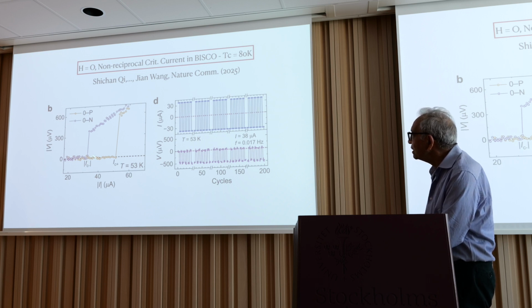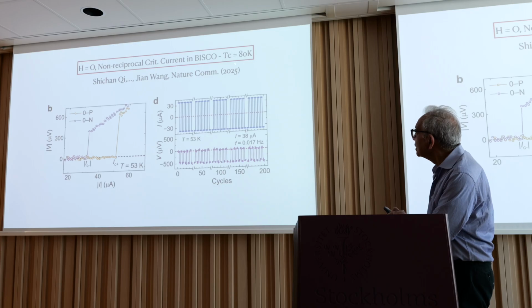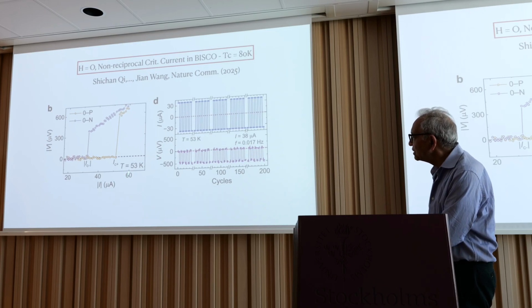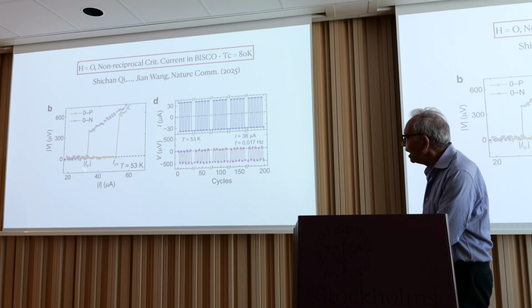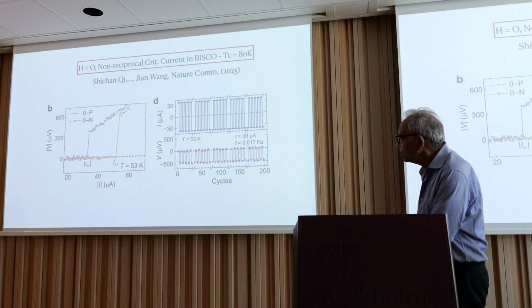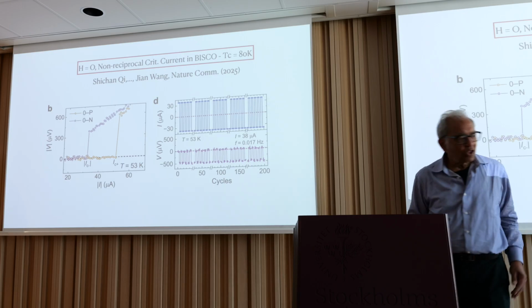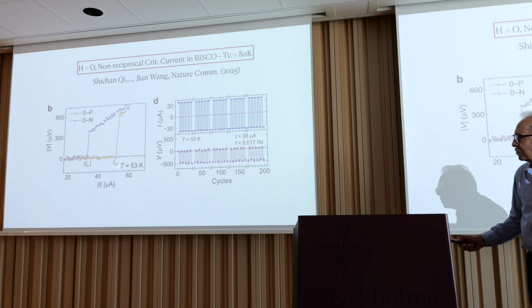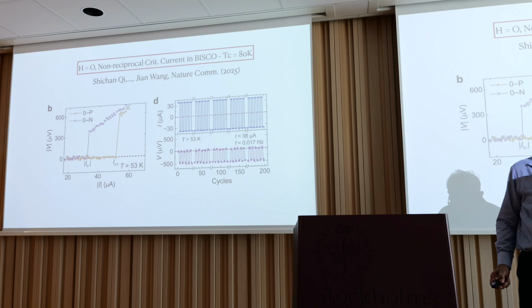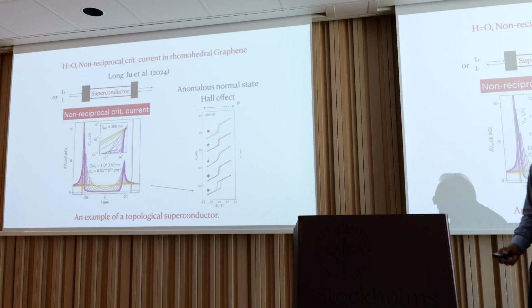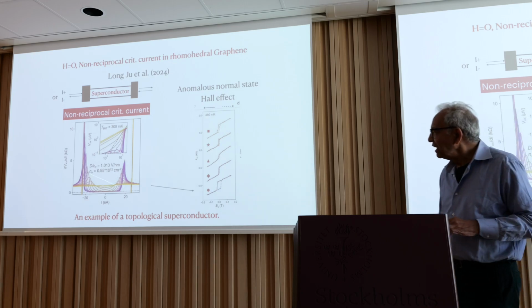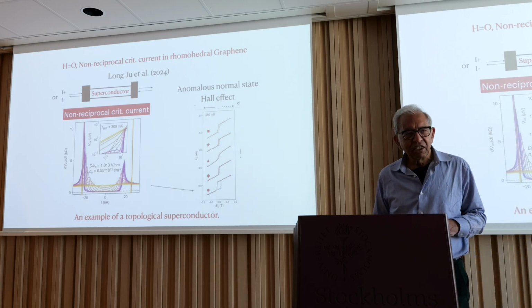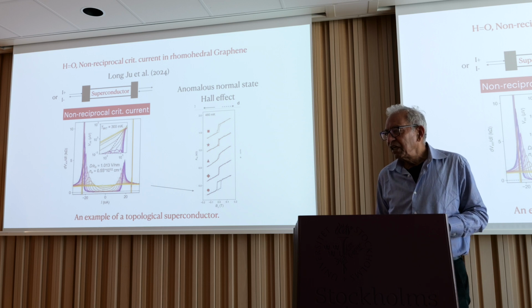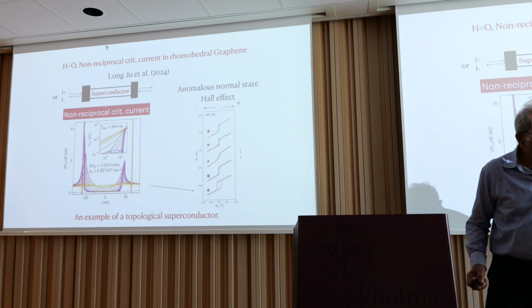that this superconductor with an underdoped Tc of 80 Kelvin, this measurement is taken at 53 Kelvin, and you observe a huge value of the non-reciprocal critical current. You see that it's on the scale of 20 microamps. The previous thing was a few nanoamps, okay, in the rhombohedral graphene. Having this very large